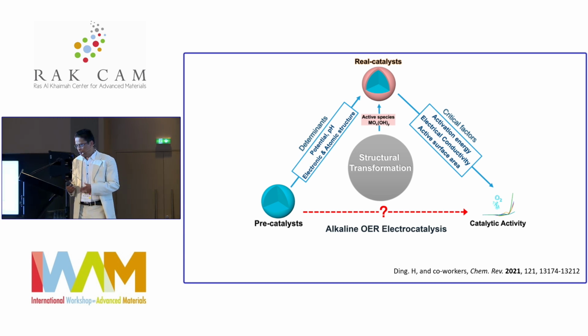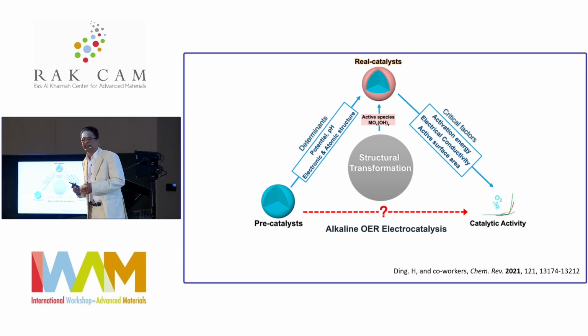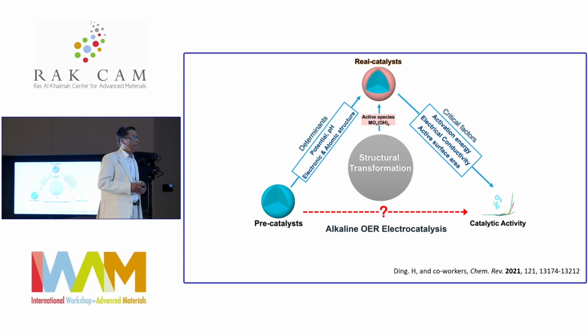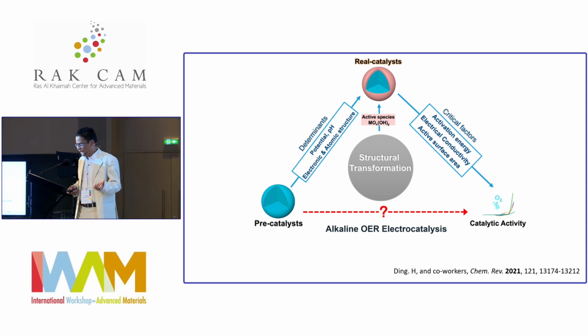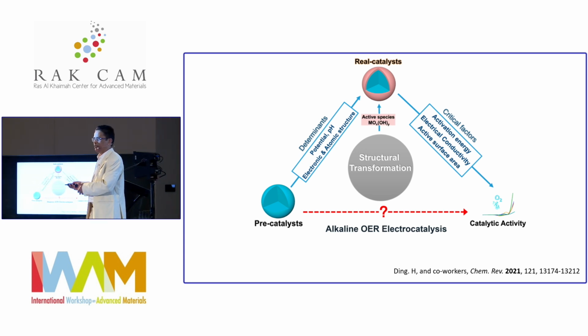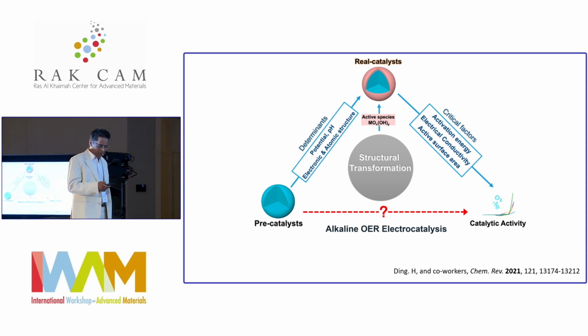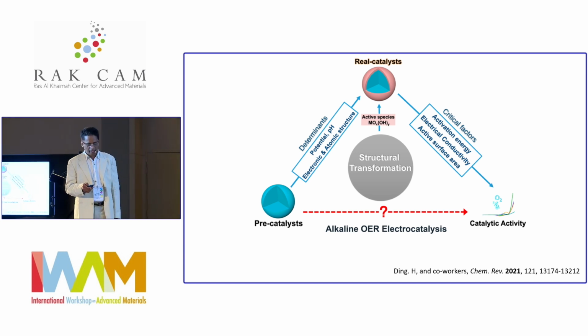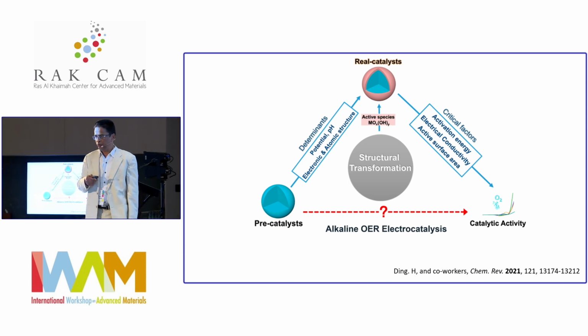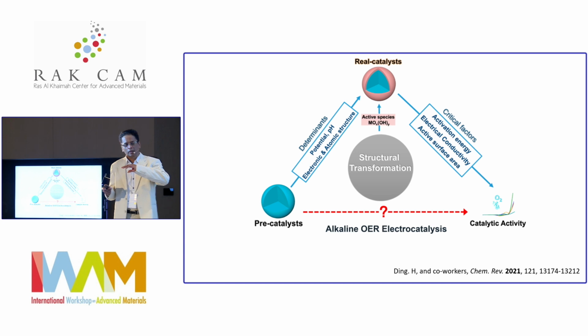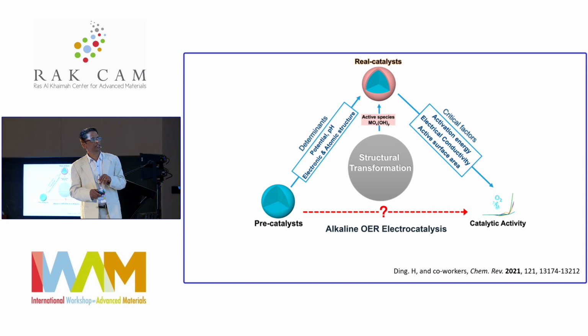Since it is a phosphide, will it be stable? Because in electrocatalysis, many of the materials, when applying the potential, are subject to this transformation. In fact, many times you'll see that it's a pre-catalyst. What is the actual catalyst? We have to wait after a few cycles. In this case, with the phosphide also, we have done such a study where we have seen that when you treat it in these conditions for a few cycles, the surface gets oxidized. It develops a hydroxy surface, and then this transformation happens in alkaline medium.